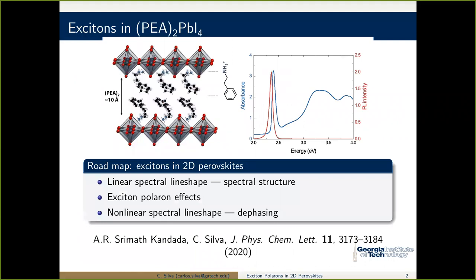So really the story is about this class of materials. This is a two-dimensional metal halide, and in this case, a lead iodide perovskite, which is a misnomer. It's really not by any means a perovskite, of course. But the idea is that we start with a perovskite-like structure in three dimensions, with a lead iodide forming these corner sharing octahedra with organic cations in between in the voids. And we take a single layer, single lattice planes of these, and separate them with longer cations. In this case, there's this phenylethyl ammonium that separates different layers of the corner sharing octahedra of lead iodide.